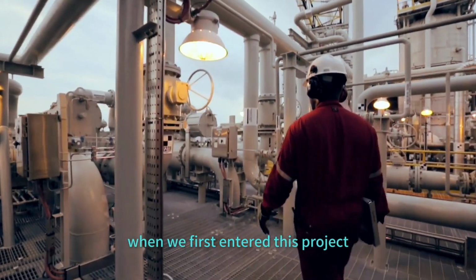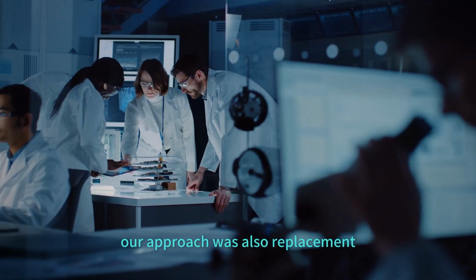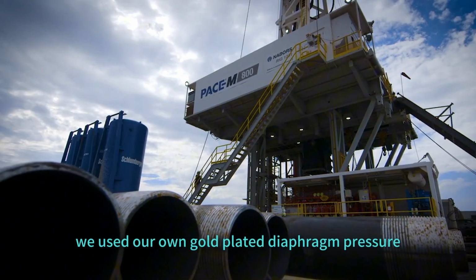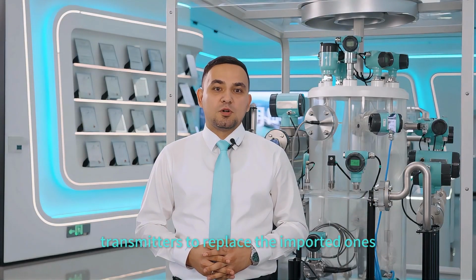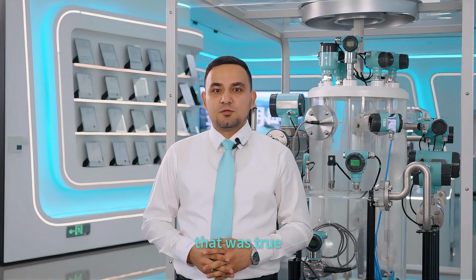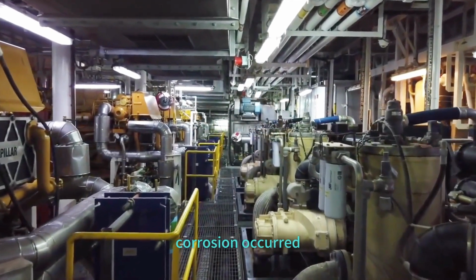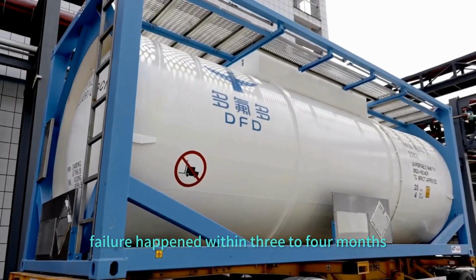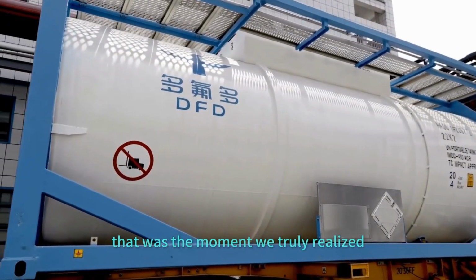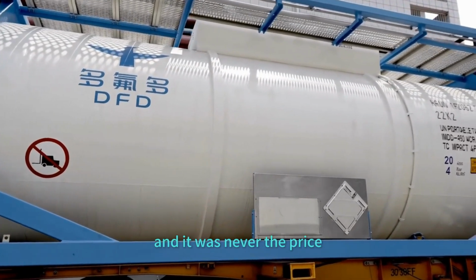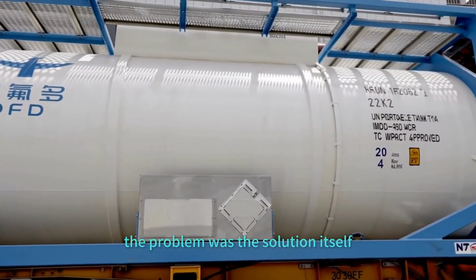When we first entered this project, our approach was also replacement. We used our own gold-plated diaphragm pressure transmitters to replace the imported ones. Lower cost for us, that was true. But after installation, the result was exactly the same. Corrosion occurred, failure happened within 3 to 4 months. That was the moment we truly realized: the problem was never the brand, and it was never the price. The problem was the solution itself.